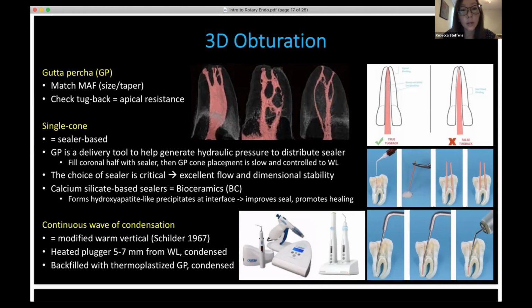For this technique, though, I do recommend that the choice of sealer is pretty critical. You want one that has excellent flow and dimensional stability. So these calcium silicate based sealers, bioceramics is a term you may see, or bioactive. Again, it's important to look at the manufacturer information, look online, and be educated about what material you're using if you're going to choose to do this technique. What these bioceramics offer is that they form hydroxyapatite-like precipitates at these interfaces, which has been shown to improve the seal and promote healing. So sometimes I'm doing this technique, like I said, case selectively.